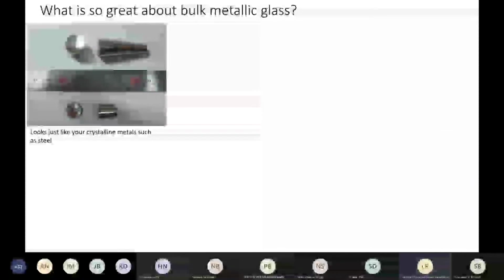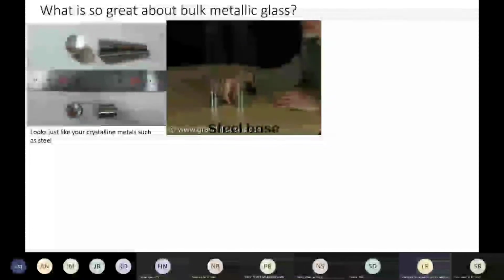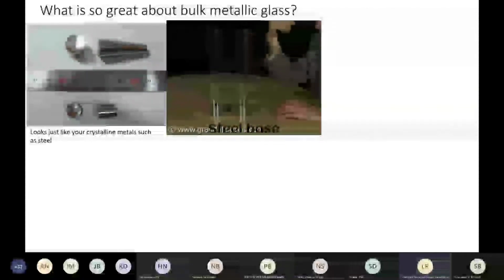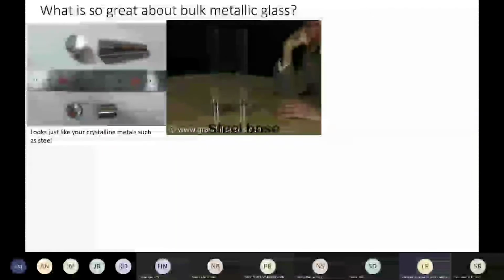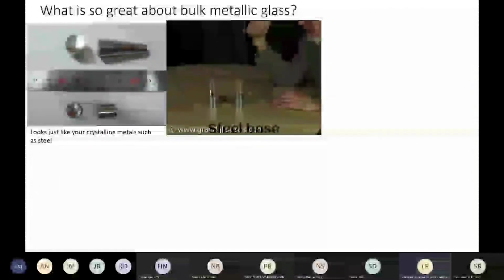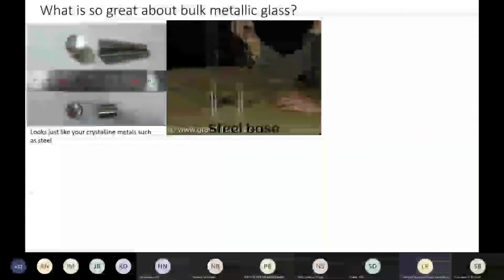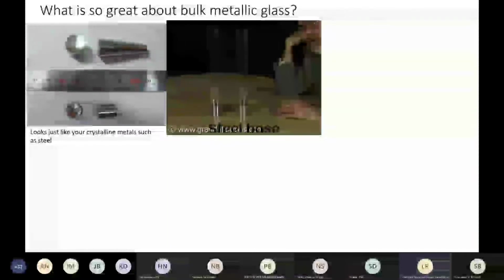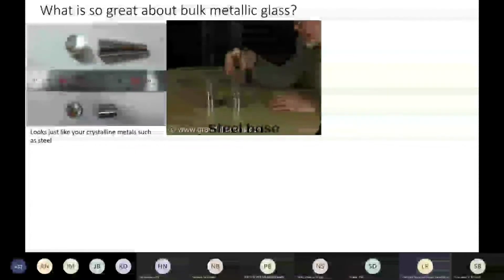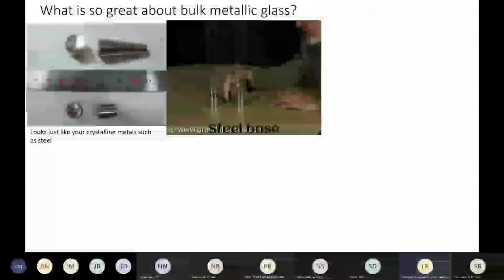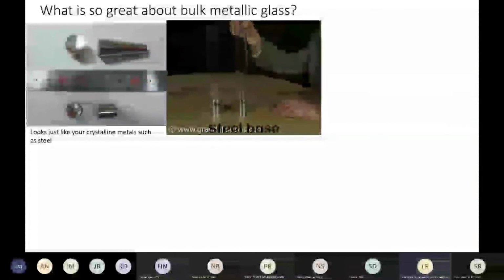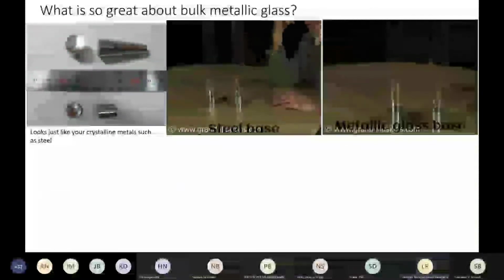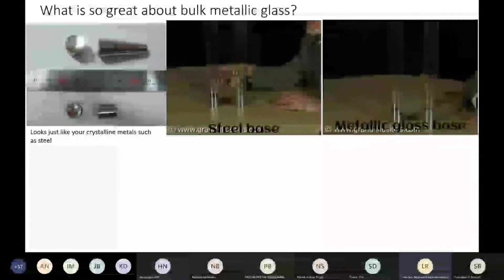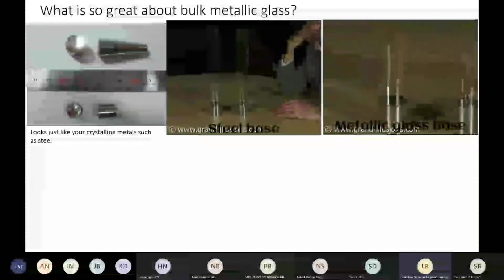Now, the difference is that when you have a steel base and you drop a ball bearing over the steel base, you see that the ball only bounces a few times. I will leave this GIF in front of you. You can just observe that when this person drops the steel ball over the steel plate, it bounces about 4 times. But when you do the same on a metallic glass base, you see that the ball keeps bouncing on it.